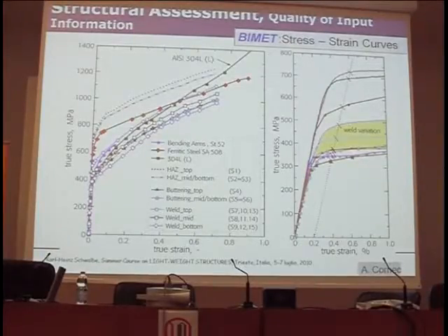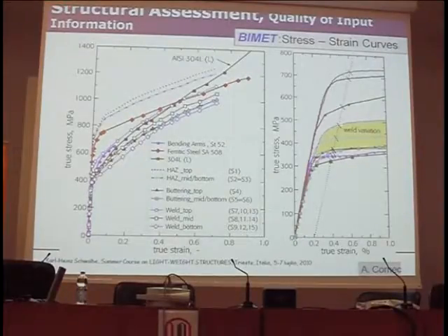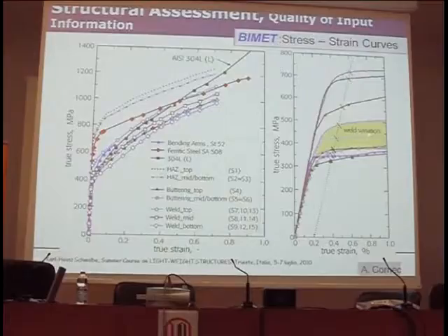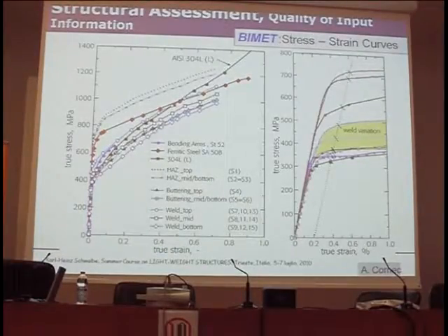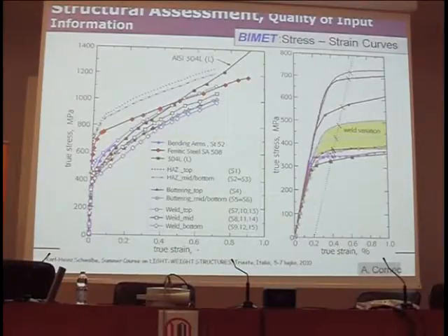And you see, this is the weld metal, the variability within the weld metal, top and down and left and right. And here are the various, doesn't make sense to go to the details here. You see which is a mismatch from 300 to 700, more than a factor of 2.